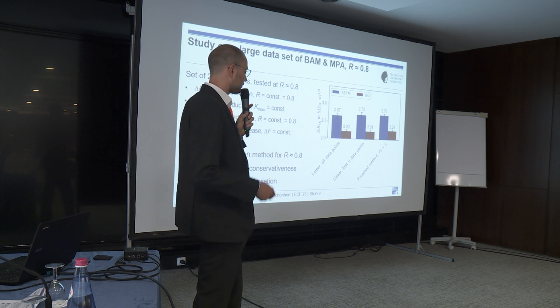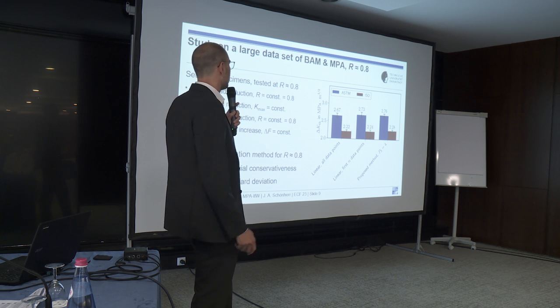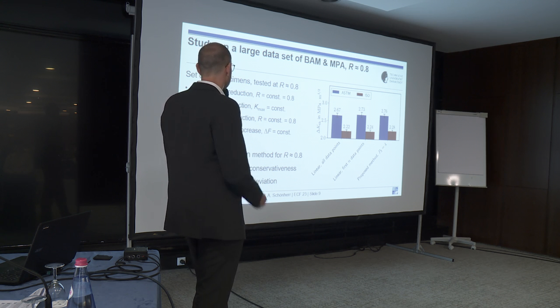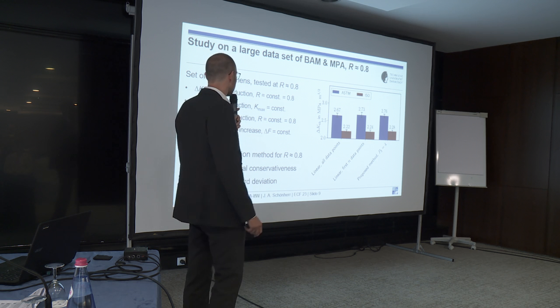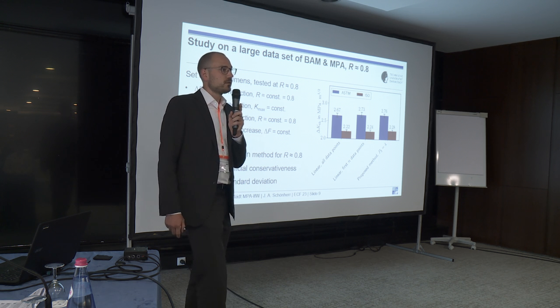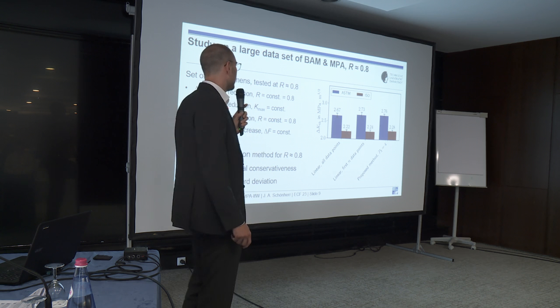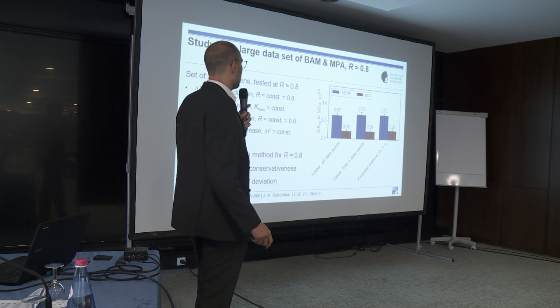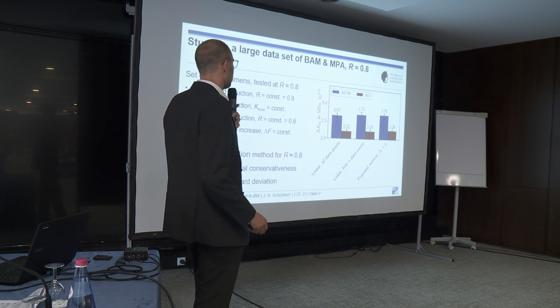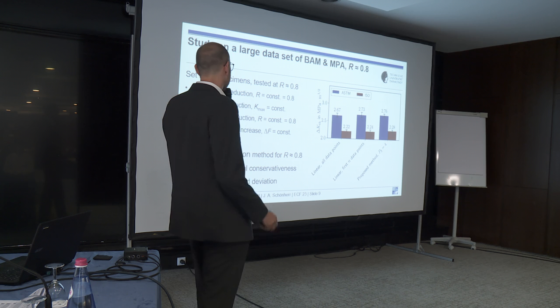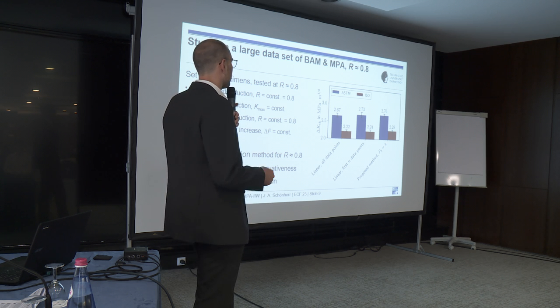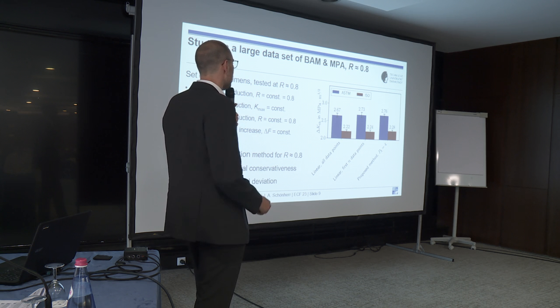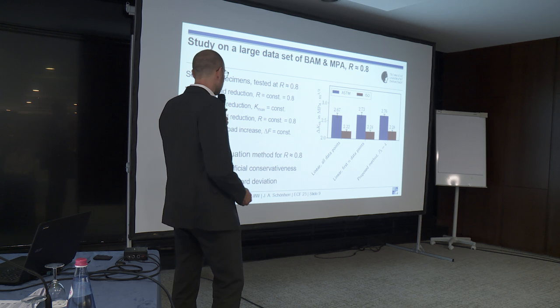We measured data during a research project with BAM in Berlin, with a total of 29 specimens — representing about one year of total machine runtime to obtain this data. The linear fits show a higher standard deviation as well as a lower threshold for both ASTM and ISO thresholds compared to our polynomial fit, demonstrating its improved performance.